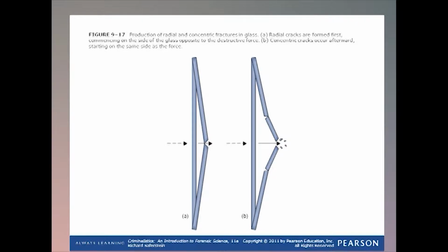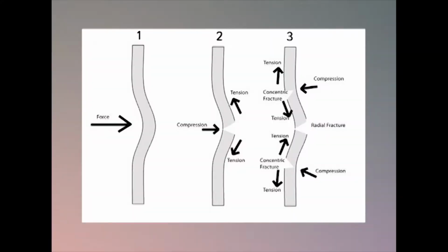Then come the glass fractures. Now, depending on whether the fracture is caused by a high velocity projectile or a low velocity projectile, there are different kinds of fractures. First is the radial fracture. Radial fractures are produced on the surface opposite to the one where the force had been applied. When an external force is applied on one side of a glass, then the glass sheet bends away from the force so that tensile stresses are set up in the opposite surface of the sheet, while compressive stresses are developed on the surface to which the force has been applied.